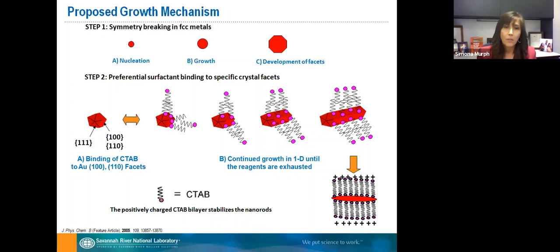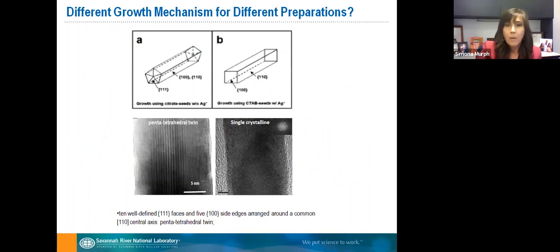So it's not only the CTAB that is critical in tuning the length of these nanorods, but like I said, everything is really important. What we found is that the ends of these nanorods have 111 facets, and they grow on the 110 and 100 facets. That's the proposed mechanism by which we think these nanorods grow. But when we compared the short rods with the long rods, they have different crystallinity. The short rods, prepared in the presence of silver ions, are single crystal, while the other ones are pentatwin crystals.